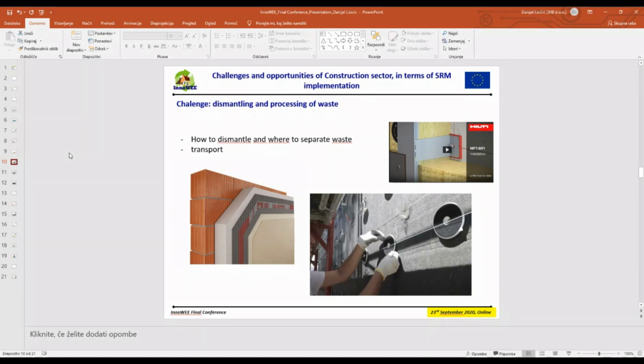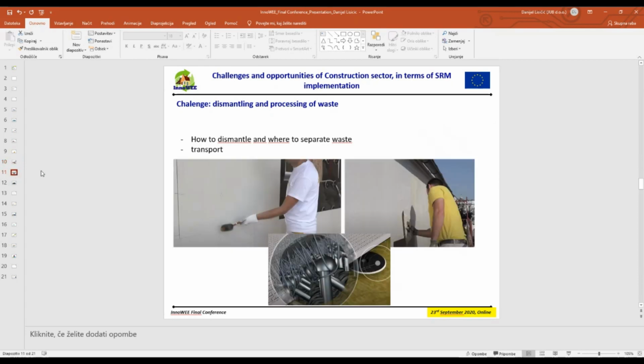You can see a solution from the company Stowe where insulation is mechanically fixed to the wall by anchors. Then special anchors in combination with boards with a hook and loop surface were developed. You can see this on this slide. And at the end, you get the classical look when you apply mortar.